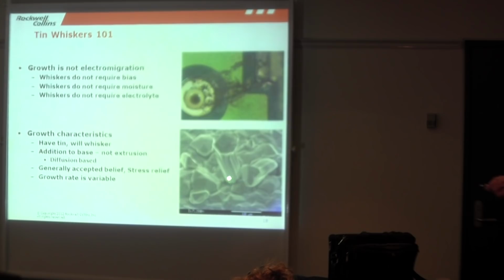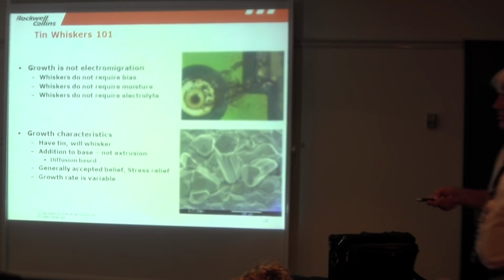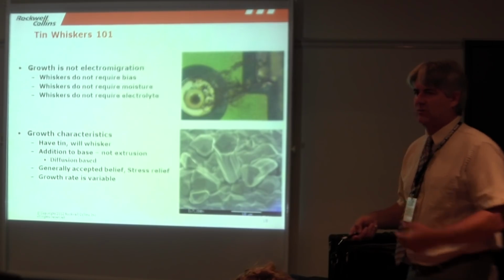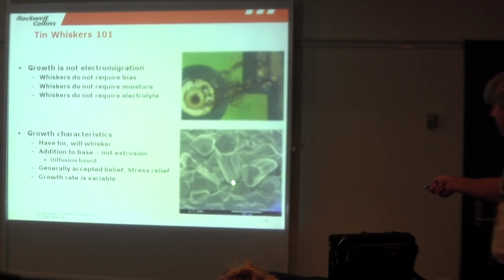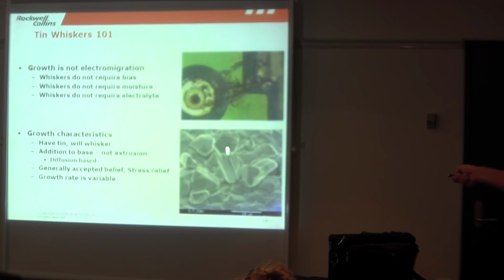It's a diffusion thing. Early on, when we got back into whiskers, if you look back at the historical record, the guys at Bell Labs say, oh yeah, these grow from the bottom. And so people are looking at this trying to think, well, if it's growing from down here, all the material is growing here, this whisker is coming out of the surface, shouldn't there be a hole? All those atoms had to come from somewhere. And Dr. Tom Woodrow did some work out of Boeing, and he shows that the atoms that add on and make up the bulk of a whisker come from a huge area.